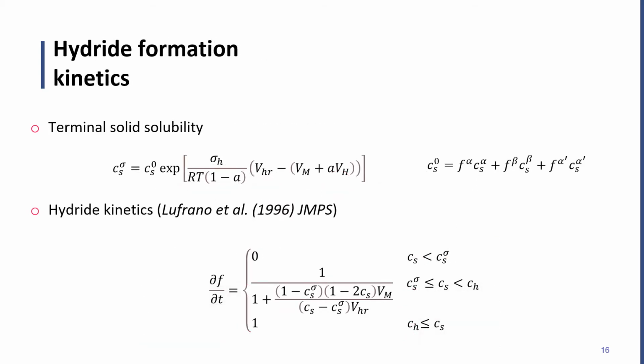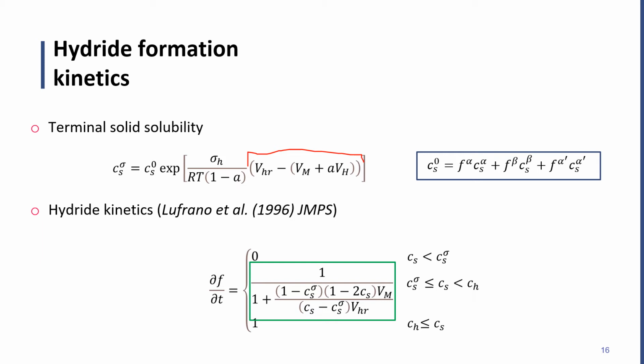Now I'm going to briefly mention two key points for hydride formation modeling. The terminal solid solubility is the concentration at which hydride formation starts, and this value depends on hydrostatic stress. We must notice that this term, for the common parameters, is always negative, so the higher the hydrostatic stress, the lower the terminal solid solubility. Another important aspect is that a rule of mixtures is considered for the equilibrium solubility. The rate of hydride formation is determined by a simple lever rule until the concentration reaches the limit value for hydrogen atoms. All this framework follows the work of Lufrano, so more details can be found in this reference.